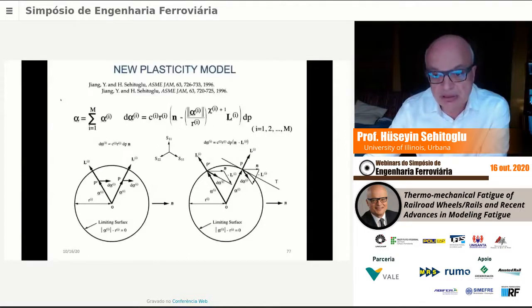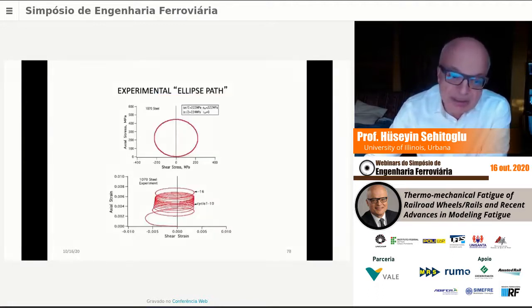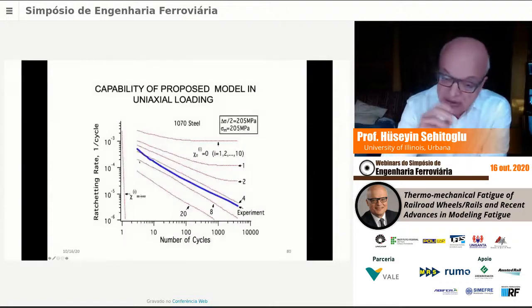It's the evolution of the back stress that we spent a lot of time on with Yanyao Jiang, and we postulated that this evolution can be broken up into multiple components, and that's been known. But if the value of alpha is small, then it follows the normality. But if the value of alpha exceeds some characteristic limiting surface, then the alpha kind of recovers a little bit. It tries to return to itself, closer to zero. As you see here, this d alpha is directed closer to zero, while here it's not directed towards zero. So that's one of the ways physically to incorporate this ratcheting rate decay.